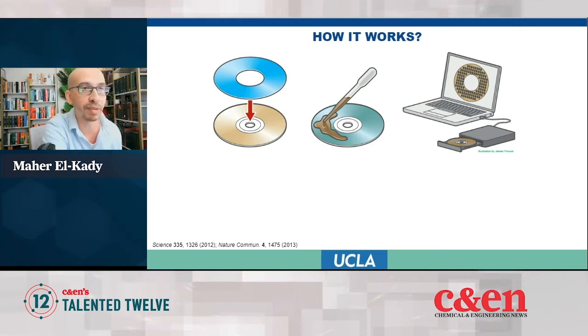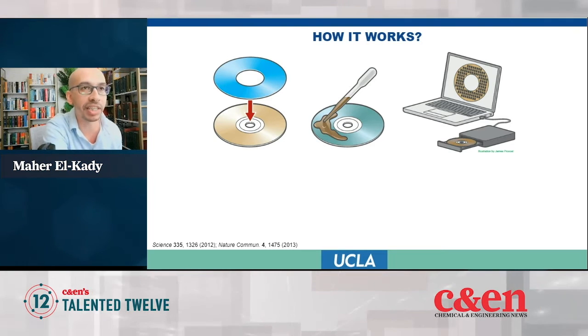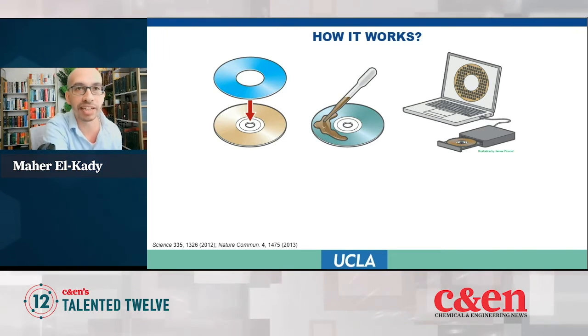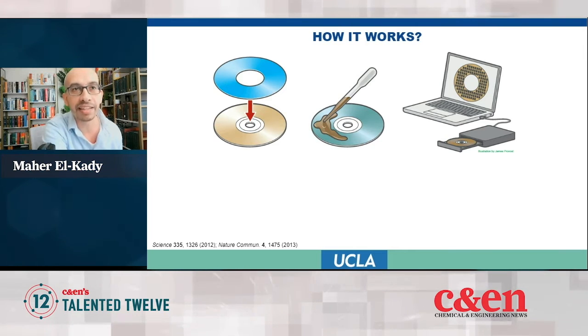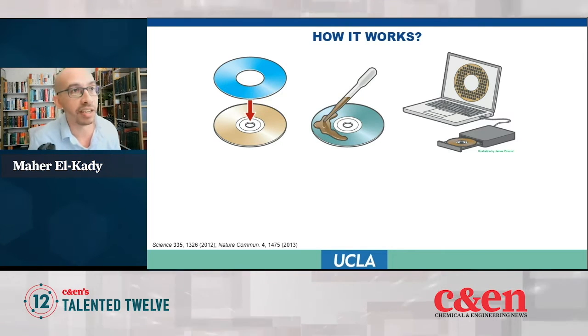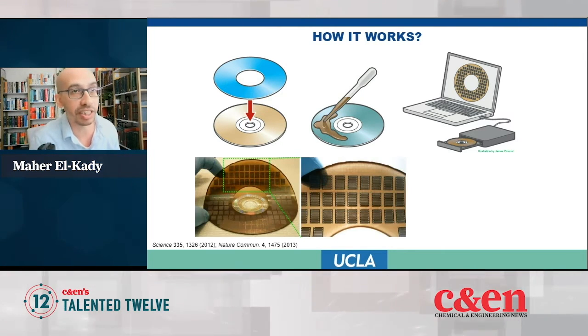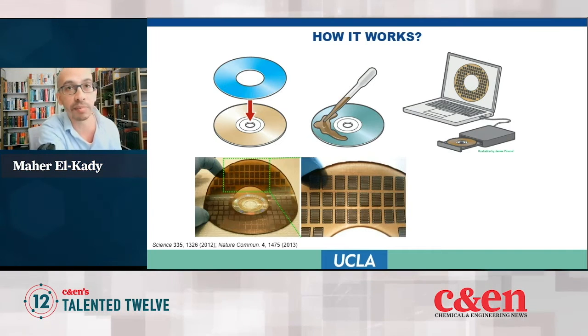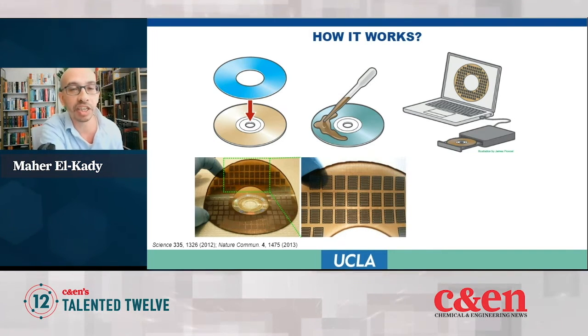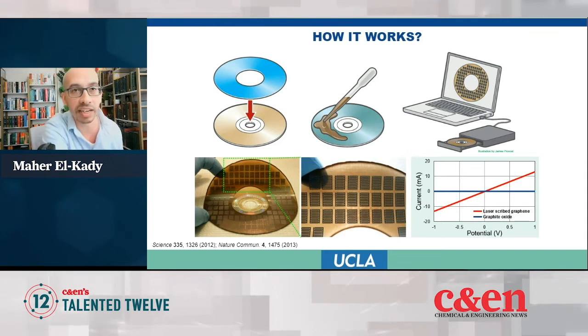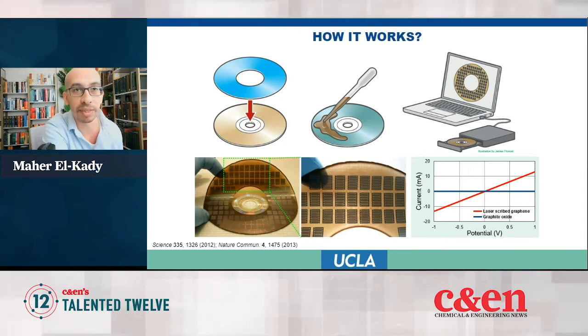The process is very simple. We have a DVD disc, we put a sheet of plastic on it, and then cast graphite oxide dispersion, let it dry, put it in the drive, and then tell the computer to draw graphene. Graphite oxide is a brown gel, and after it's been hit with a laser, it becomes graphene, and it's actually changing its electrical properties from insulating to conductive after laser scribing.